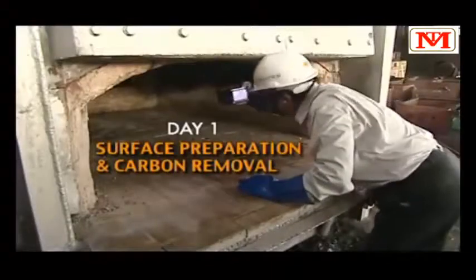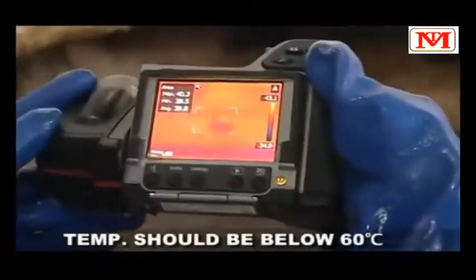Total implementation cycle takes 3 days time. This is day 1. Our furnace surface temperature is below 60 degrees Celsius. Today we will start with surface preparation, which includes removing carbon and other dirts from the refractory lining and leveling the refractory surface.